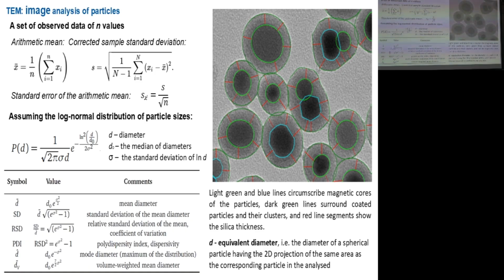So just another recommendation: when reporting values like this, you should really state what you are reporting. So I really recommend to use either clear nomenclature like this and this, or to include at least in supplementary some definitions like this, because the literature is again flooded with some standard deviations, some reported standard errors, but there are different approaches, and if you do not declare, or if you just mention some deviation or put some number in parentheses, it has absolutely no value if the reader doesn't know what you are speaking about.